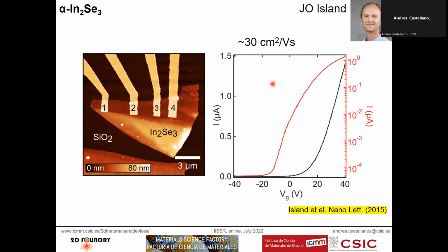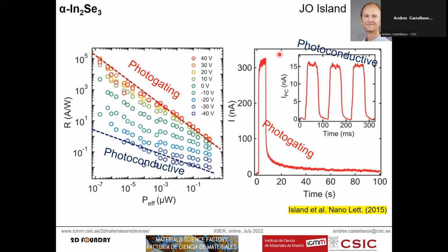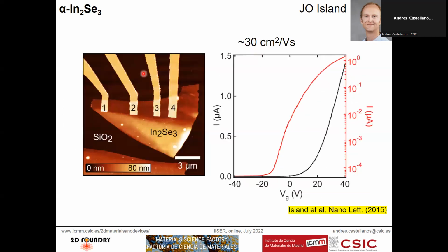So, which means that we are underestimating the mobility because of the contact resistance. Okay, so these values here are quite good in comparison with moly disulfide. At room temperature in moly disulfide, we get something between 0.1 and 10 centimeters square per volt per second. Now, this material has this N-type doping.